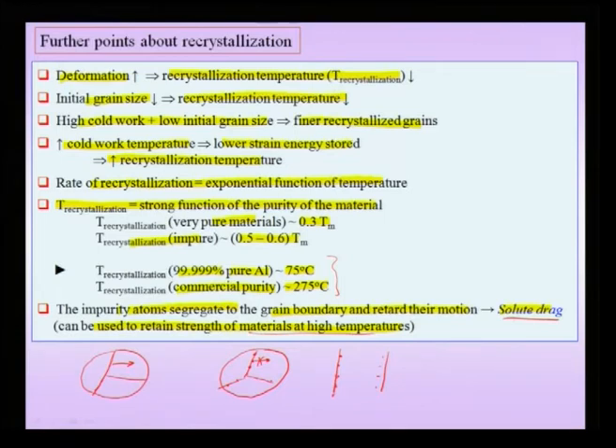Additionally, we had also noted that the rate of recrystallization is an exponential function of temperature, and it looks like an Arrhenius equation. But this activation energy, as we should note, is representative of very many complex processes taking place and should not be interpreted in simple terms, as if recrystallization were a single fundamental process.